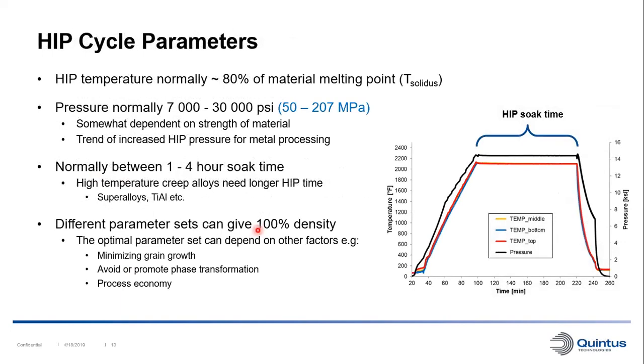Here we're going to go through some of the typical HIP cycle parameters used. So the HIP temperature is normally around 80% of the melting point. That is the solidus temperature of the material. The pressure is normally ranging between 7,000 and 30,000 psi for castings. This is somewhat depending on the strength of the material. So, for example, when I HIP ceramics in our lab here, I normally go with the highest pressure. The soak time in the process is typically between 1 and 4 hours. Most metals are sufficient to have a 2-hour soak time and get full densification.